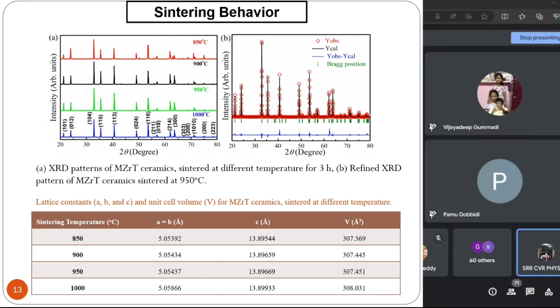So we have seen that the density of the material is coming up nicely, and there is no secondary phase even after densification. The right-hand side is the figure of the XRD pattern. We have refined it with Rietveld refinement in order to find out if there is any secondary phase or not. We found that there is no secondary phase, it is a pure phase.